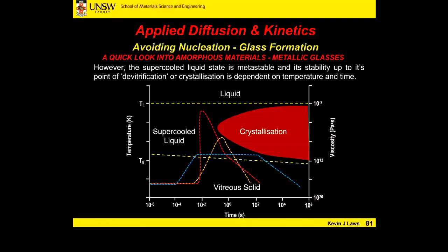What would happen to the material, if you have your little test tube of metal and you're trying to blow it into your perfume, what happens if you hit that crystallization point? Does it just rapidly proceed to form material? So once crystallization occurs, those crystals will grow. But in terms of formability, it becomes a composite structure. Then those crystal nuclei are now in the way of Newtonian flow or viscous flow. Basically, once you exceed 10% crystallized volume fractions, you start to see tearing in the material.